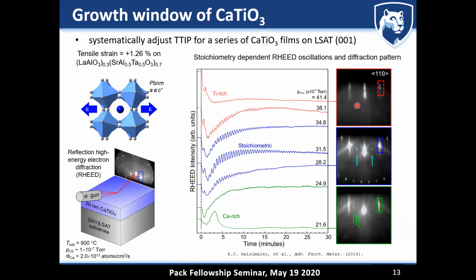And then the other thing that we see is that we can distinguish different types of surface reconstructions depending on the flux of calcium, which is fixed, and the amount of TTIP that we are supplying as we grow. So you can see that under a very specific condition, which later on turned out to be stoichiometric, we see a 2× reconstruction as we look at the diffraction image down the 110 azimuth. We are losing this 2× reconstruction, this extra peak, as we become too titanium rich, and we change the reconstruction on the surface to a 4× reconstruction. You can see here 3 side diffraction streaks as we go into a calcium-rich condition. So really this means that we have stoichiometric control over our film growth as we grow.